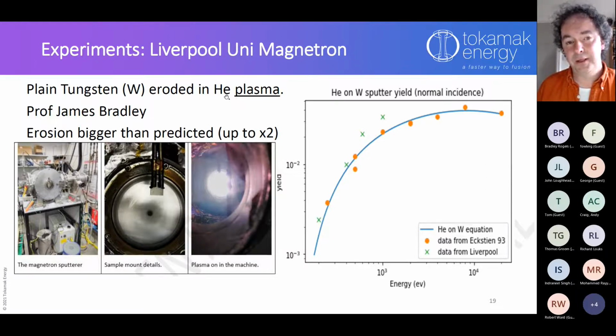The helium plasma is a bit different from the helium ion beam in that the plasma is much more diffuse, whereas the ion beam is a very focused beam of ions. Can't think of a better word than that. In the plasma, we are able to measure the sputter yield by weight measurement. We take the weight before and after, and Professor Bradley's team did that for us, or well, they did most of the work, to be honest about it.